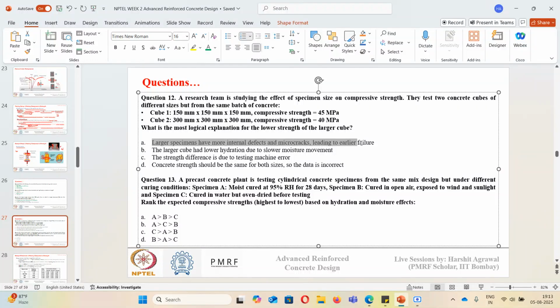Okay, yes, for 12, the correct answer is A. In this question, two cubes of different size were given. The first was 150 cross 150 mm, and the second is 300 cross 300 mm. We observed that the smaller cube has a higher strength compared to the larger cube. The reason for this is the size of the cube. The larger the size of the cube, the higher the chances of having internal defects and micro cracks, which can lead to early failure.